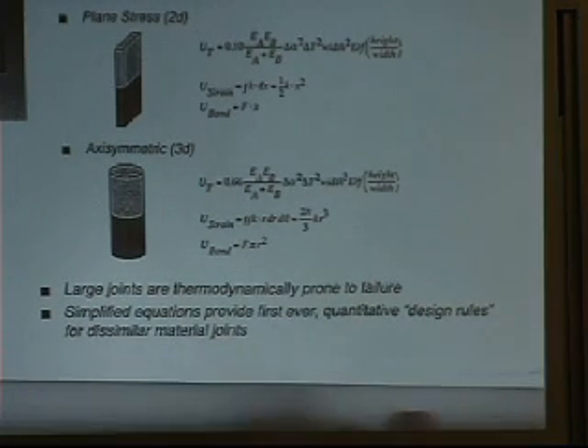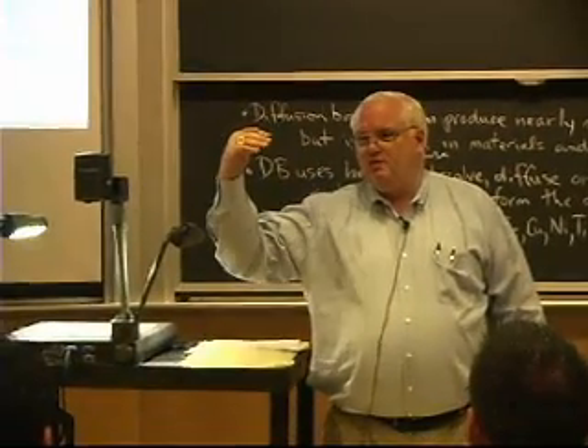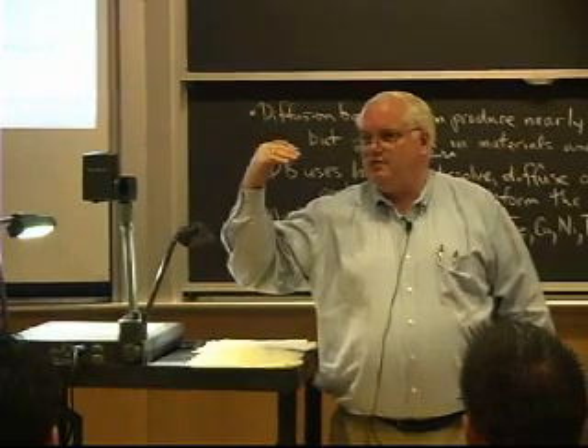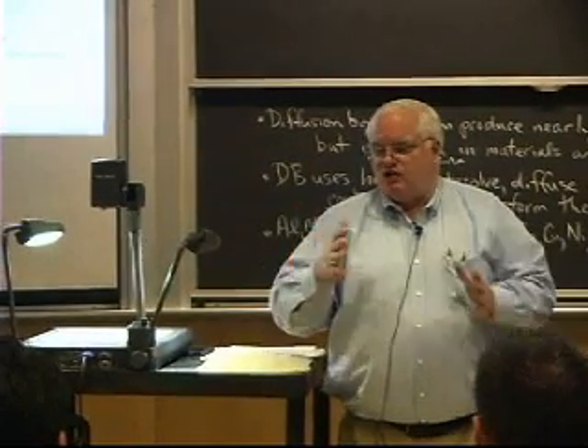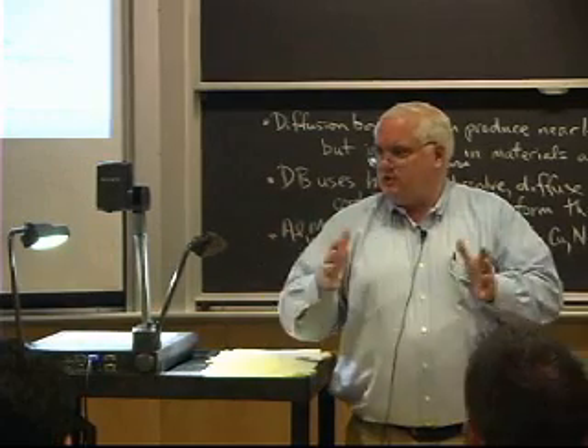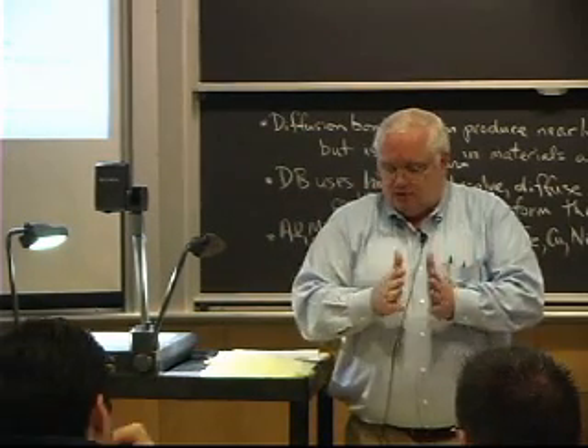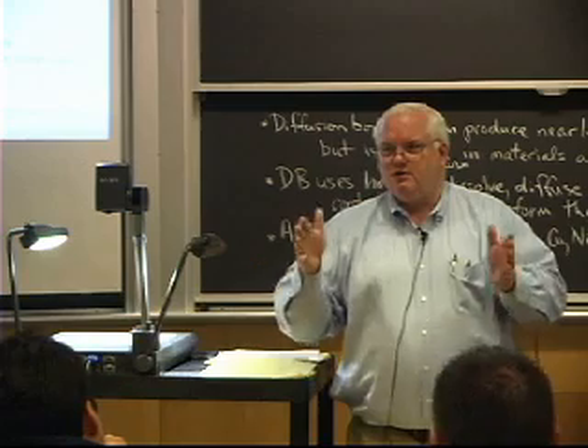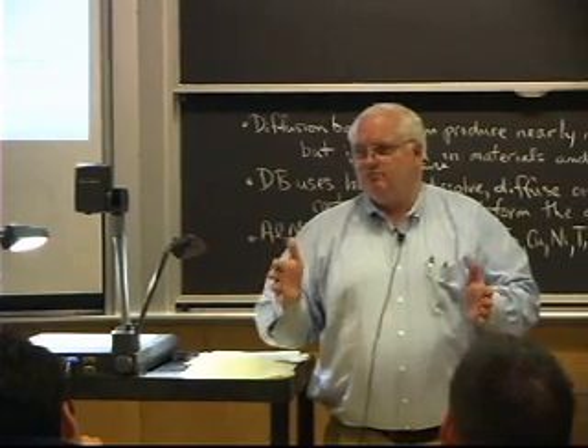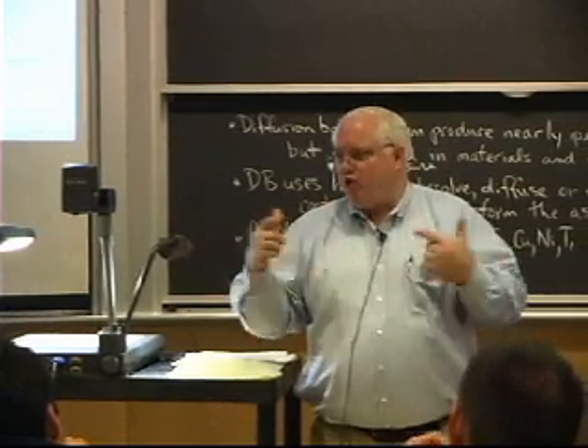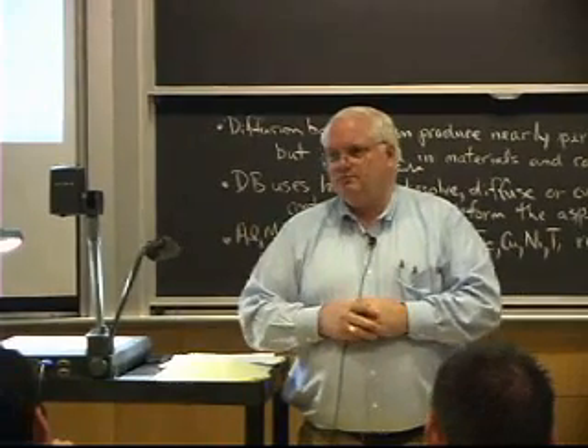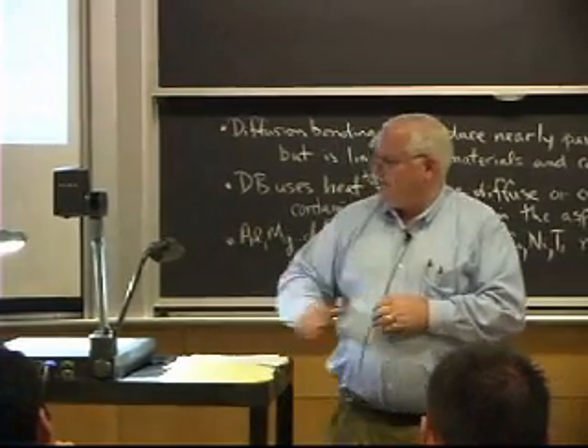And if you looked at it axisymmetrically, you'd find the strain energy goes as r cubed, and the bond energy goes as the area, which is r squared. And it doesn't matter whether you're two-dimensional or three-dimensional, the strain energy builds up at one length dimension higher than the strength of the joint. And the strain energy is what causes the thermal expansion problems. And what that means in a practical sense is the bigger the bonded area, the worse the thermal expansion mismatch gets. And it's going to be proportional to the length dimension, okay, if you're thinking in terms of dimensional analysis.